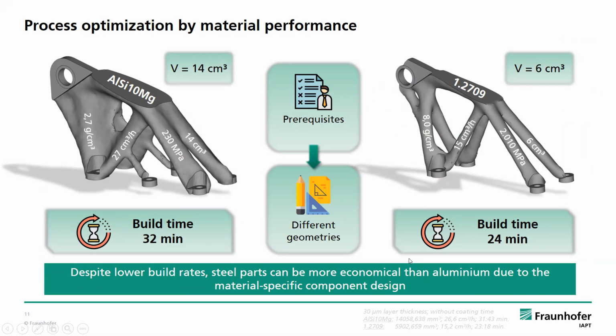And the final aspect that I want to touch briefly on is process optimization by material performance. So what do we mean by that? For a given structure that you can see here, you have the possibility to print it in aluminium alloy or steel alloy. And of course, the specific strength of the steel alloy is a lot higher. So it allows you to build with less volume and still maintain the strength prerequisites of the part. And even though, of course, scan speed for aluminium and specific weight of aluminium is a lot better compared to steel, it may still pay off to look at the alternatives because you can save material and you can still come up with higher productivity when producing such a steel part, giving you the same performance as the comparable aluminium part.